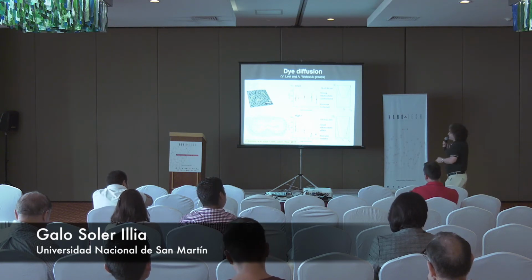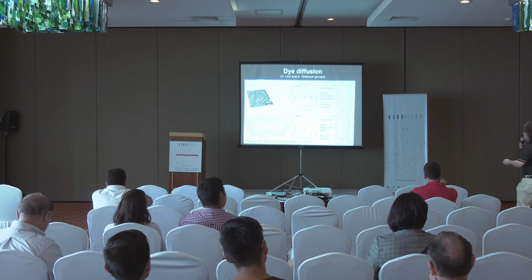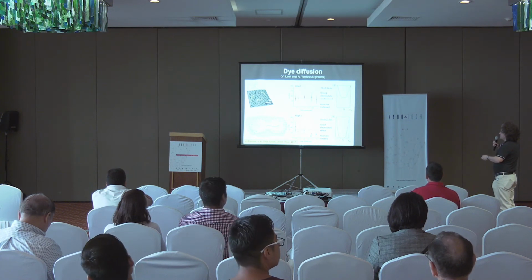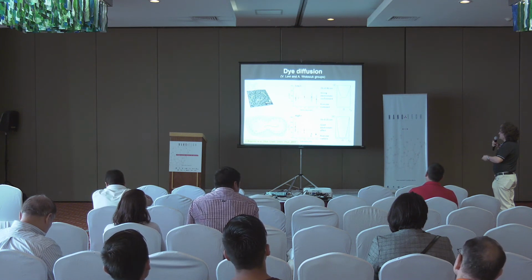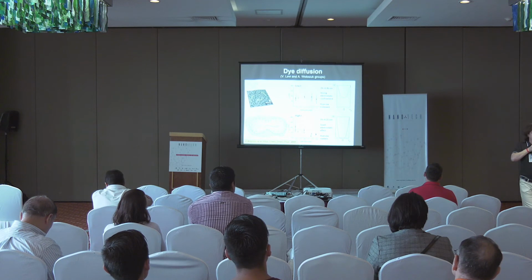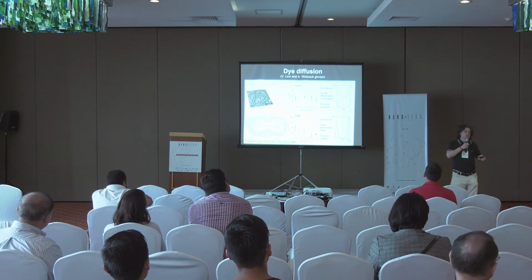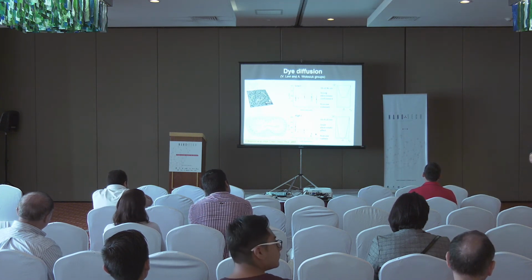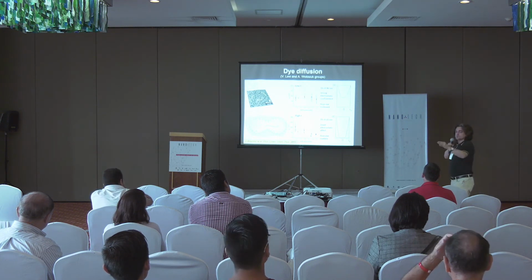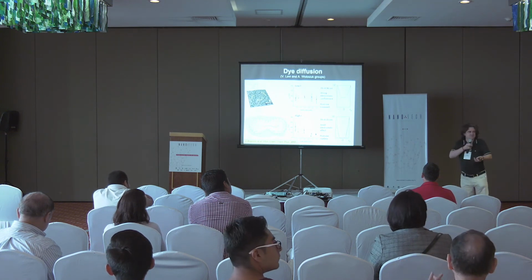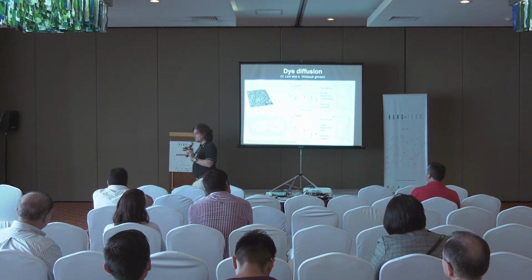When you increase the ionic force, you put more salt, you screen the charge from the pore surface, and now for small pores, yes, molecules tend to stay in small pores, but as pores get larger, the molecule residence times are lower, so the molecule goes faster. So here you see two regimes: one regime which is electrostatic, and one regime which is determined by the size of the pores. This gives you an idea. This is just one dye molecule traveling along pores, with two regimes at different salt concentrations. So whenever you are talking about sensors, it is not easy. Fundamental things are yet to be understood.